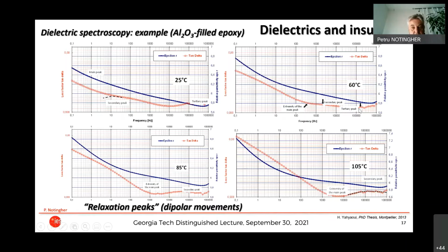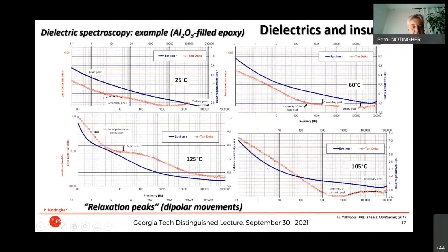So you see this peak which shifts above 100 kilohertz, and when you increase the temperature a little more, you won't see it anymore. This one will come closer and closer to the kilohertz. Here we still have the secondary peak; you see it more and more. And when you go to 125 degrees, you have the main peak, the one that you're not able to see here because it is below 0.1 hertz, and you don't see the secondary relaxation peak anymore.